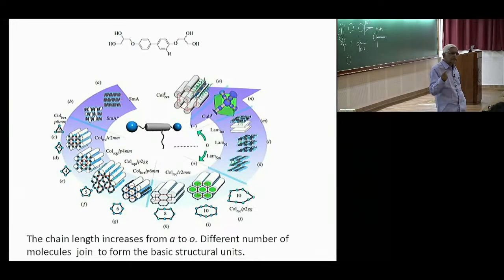These come as monomers. There is some either UV or some such thing, it polymerizes. Then you rub it gently along one direction. There are rubbing machines. One of my students, I think Surajit Dara, who is in Hyderabad, even made some rubbing machines. I don't know whether they still make it. They even sold some. So then you align it. Even in technology they use it. The 100-inch television set that you see, the alignment is done like that.